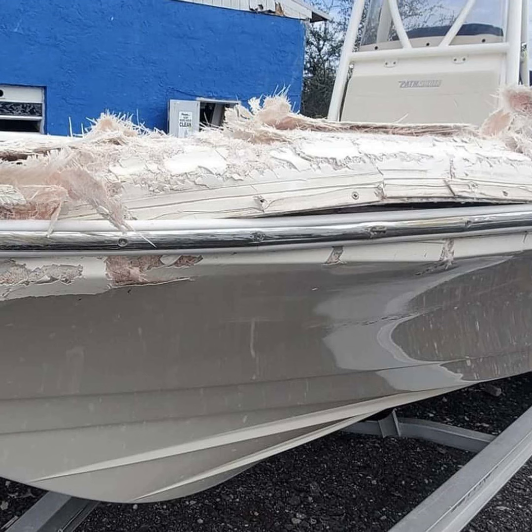Sorry, don't most resins have their time spec done per 70 degrees or a specific temperature? Yeah. So the resin that we use is spec to last 32 minutes at 70 degrees. In the wintertime, they give us the 27-minute resin, and in the summertime, they give us the 32-minute resin. And that's literally the difference between a 2,700 part number or a 3,200 part number. And ideally, that extra 5 minutes sometimes makes a difference when you're talking about the outside conditions being a little warmer.